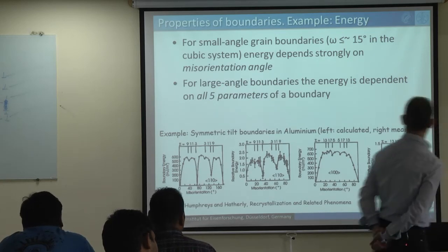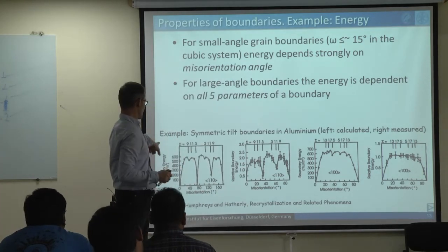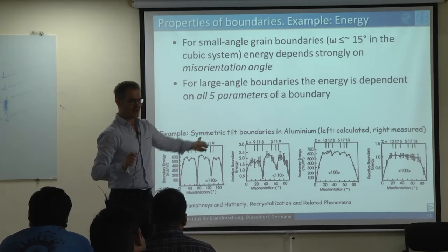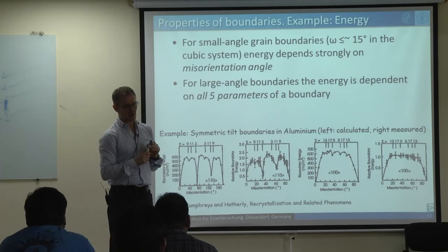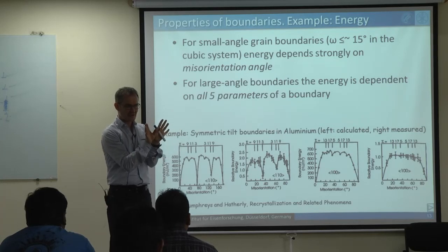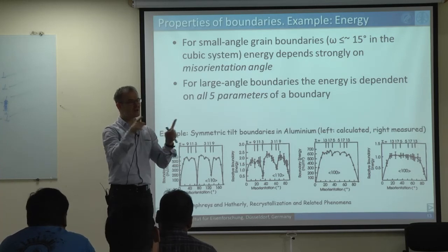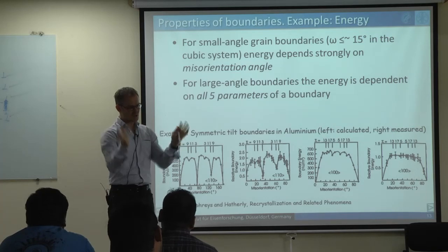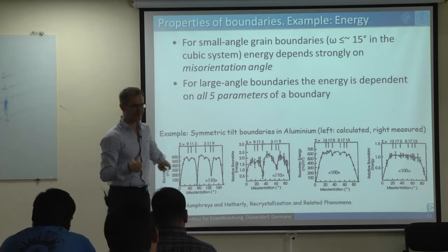How to calculate it? Nowadays it's not so complicated to calculate that. At that time, in the 60s or something like that, this was a really tough calculation. What you do nowadays is you do either ab initio or molecular dynamics. You create an atomic arrangement of this kind. You just build up an atomic lattice in the computer, and then you calculate the energy between all the atoms, and you sum it up. I say it's so easy, no? It's sometimes complicated to create the right structure.